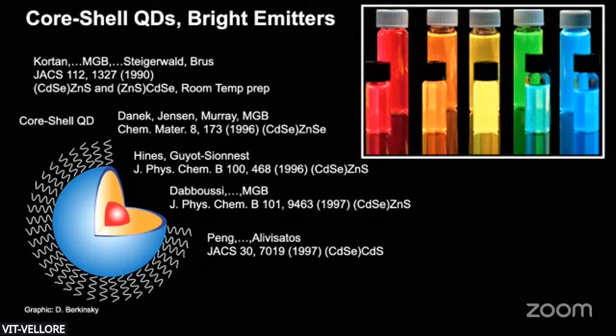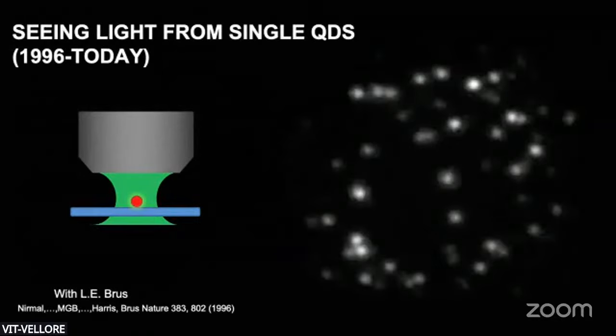It's like an M&M, it melts in your mouth, not in your hand. So we're protecting the quantum dot from the surroundings. Now we have this functional material in the center, surrounded by another material to protect it, and then organic molecules to allow it to be manipulated like a big organic molecule. That became the engineered material that we're used to making today. And the quantum yield then went up to nearly 100%.